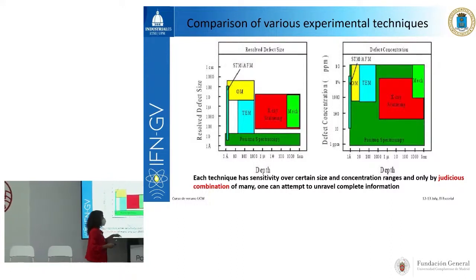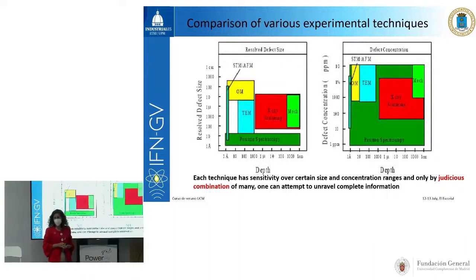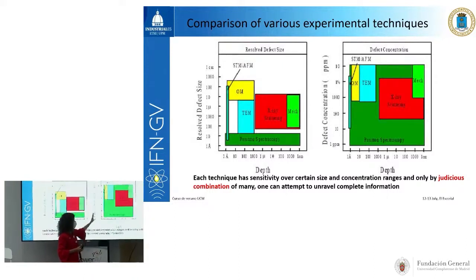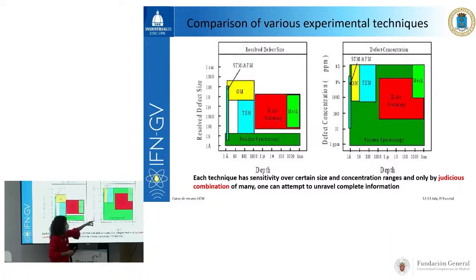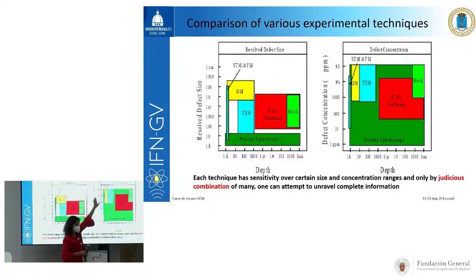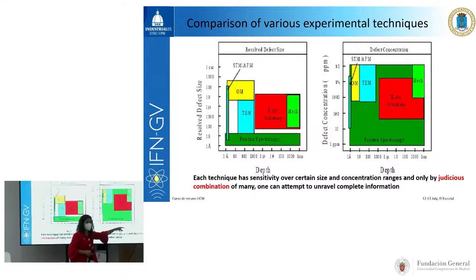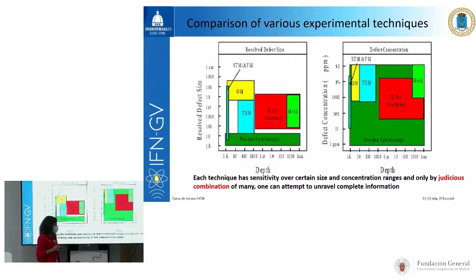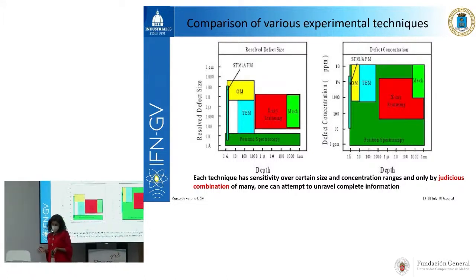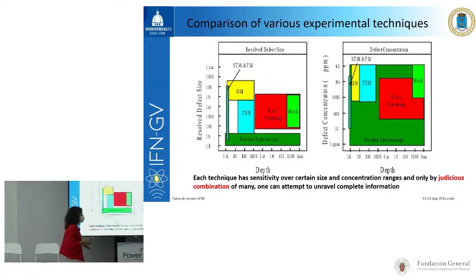And then here again, I show you a very similar picture in which I plot the defect concentration as a function of depth. You may see here 1 ppm, 10 ppm, and so on, up to 100% of the total concentration. And this is as a function of the sample depth, again, underneath the sample surface. You may see that if we want to study a very small defect concentration, then the only possibility is to go to positron spectroscopy.